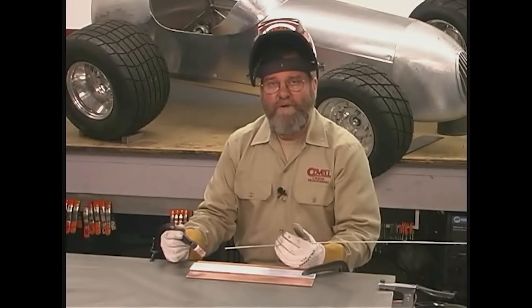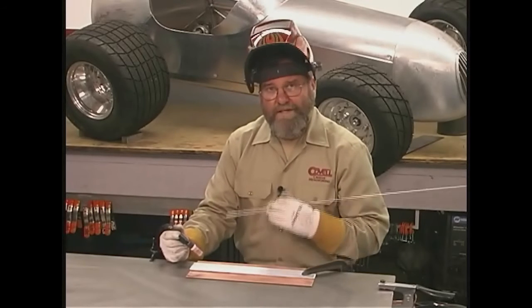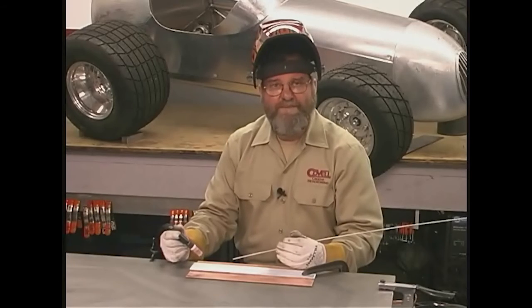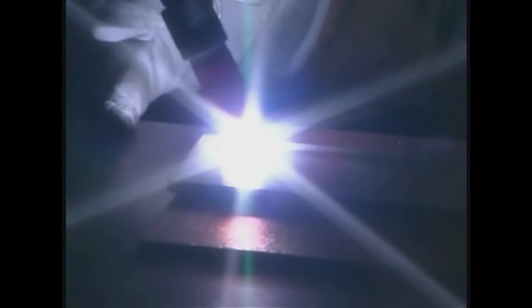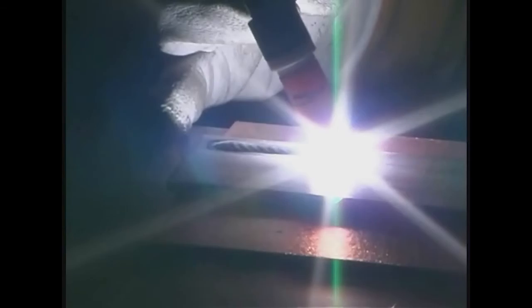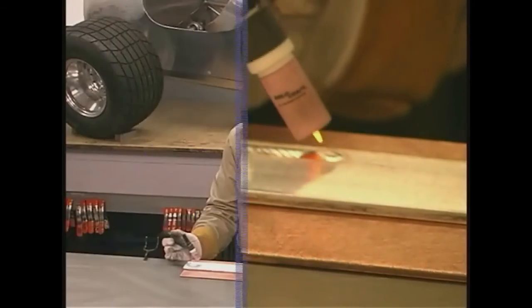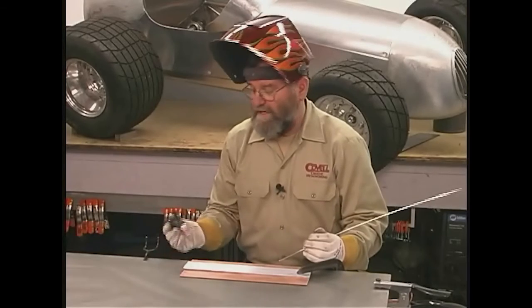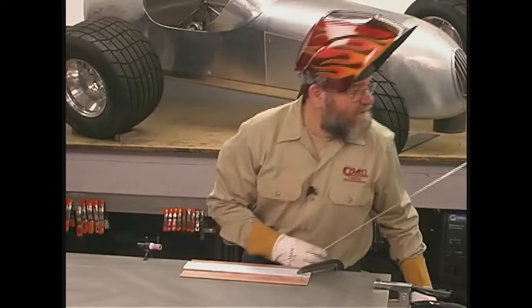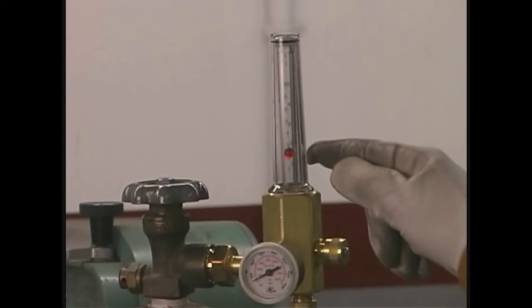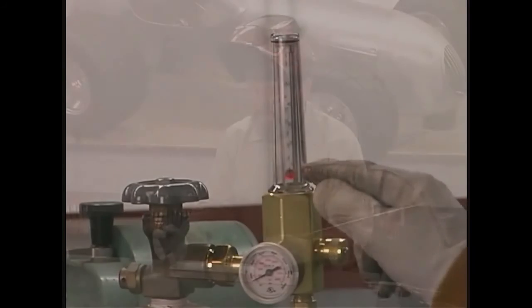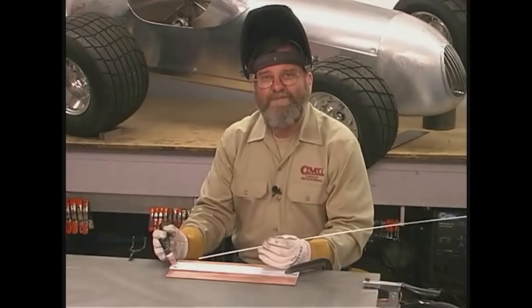The next thing we'll talk about is the importance of having a complete inert gas shield over the weld area. So I'm going to make a short weld with everything being done properly, and then we'll make another weld with not enough argon gas flowing, and you'll see a clear difference between them. So there's the weld with everything done properly. Now I'm going to make a change to the flow meter. I'm going to turn the flow meter from 18 cubic feet per hour down to about 9 cubic feet per hour. I'll make a second weld parallel to the first weld. Then we'll take a look at the difference.